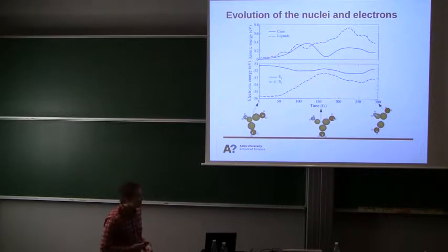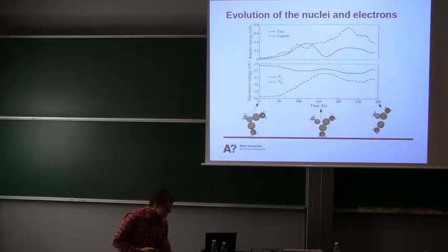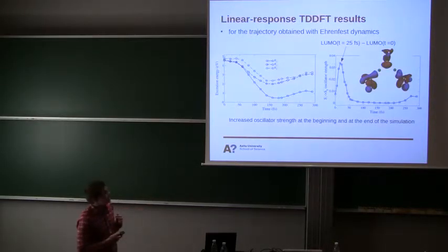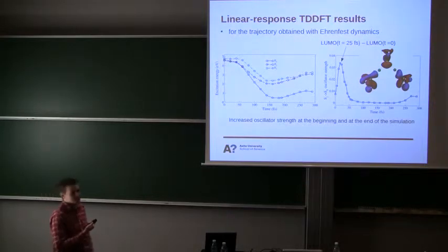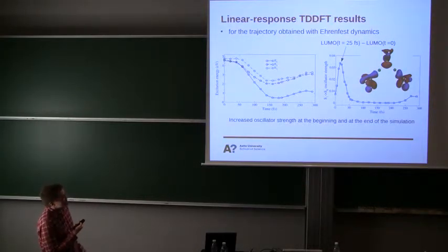Due to having different types of ligands, not just the two of them. Then we did something interesting: we calculated linear response calculations in the Ehrenfest trajectory. Our first finding was that the first three excited states were energetically very close at the beginning, but they start to separate after 150 femtoseconds or so. It's an interesting observation.